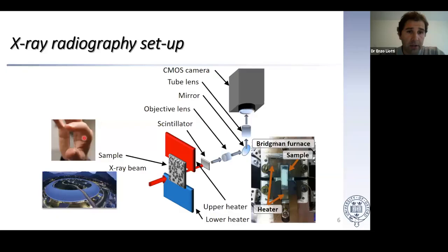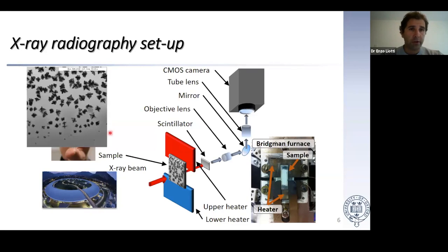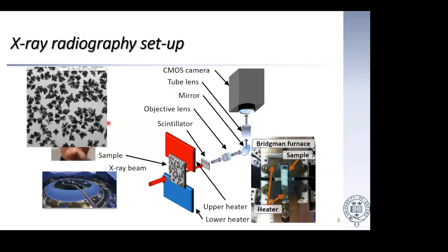It is then collected by a camera. In this setting, which is very simple, and that's why it's very useful, samples tend to be foil samples. The thickness varies, but is normally around 200 micron, and this is to maintain a single layer of grains or crystals forming and not overlapping. So if you do it well, then you can collect images or videos and obtain data.